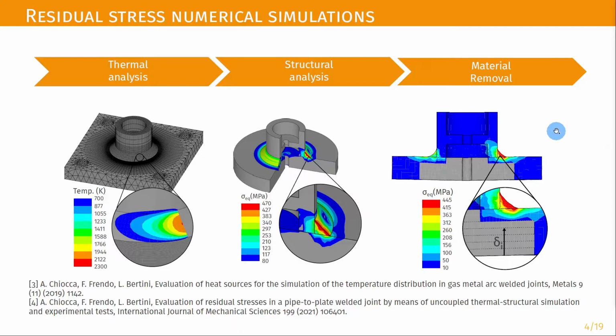Alongside the fatigue test, a numerical model was developed to determine the residual stresses that arise as a result of the welding process. The model uses an uncoupled thermostructural simulation, as you can see from the first two images, the thermal analysis and the structural analysis. This was followed by a material removal model to confirm the correctness of the results. Basically, results of relaxed strains around the weld seam were compared numerically and experimentally.